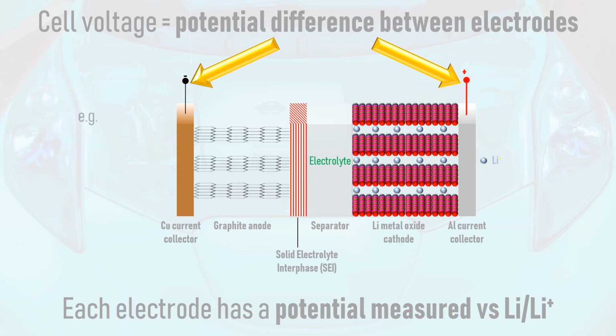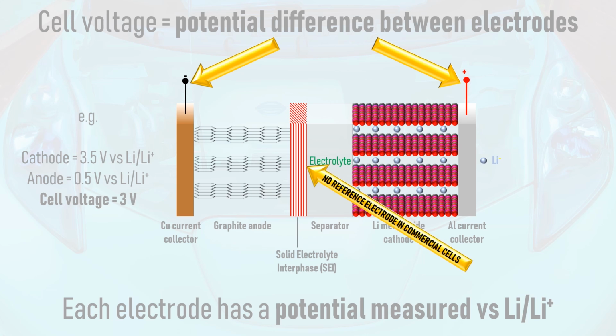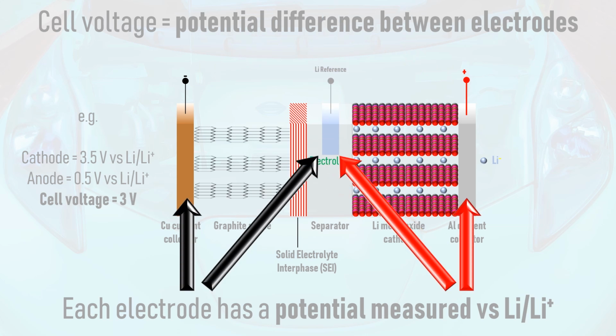For example, if the cathode potential is 3.5 volts versus lithium and the anode potential is 0.5 volts versus lithium, the full cell voltage is 3 volts. Note that only the full cell voltage, the potential difference between the two terminals, is measurable on a commercial 2-electrode lithium-ion cell. It is only by opening up the cell, adding a third reference electrode, such as one made of lithium foil, and getting the cell to behave like nothing has happened to it, that we can understand what each electrode is doing in isolation.